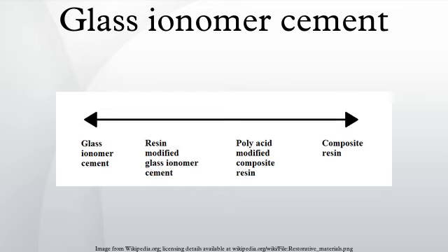Glass ionomer cements bond chemically to dentine and enamel during the setting process. The mechanism of bonding appears to involve an ionic interaction with calcium and/or phosphate ions from the surface of the enamel or dentine. Bonding is more effective with a clean surface provided cleaning does not remove an excessive amount of calcium ions. Treating dentine with an acidic conditioner followed by a dilute solution of ferric chloride improves the bonding. The cleansing agent removes the smear layer of dentine while the Fe3+ ions are deposited and increase the ionic interaction between the cement and dentin.